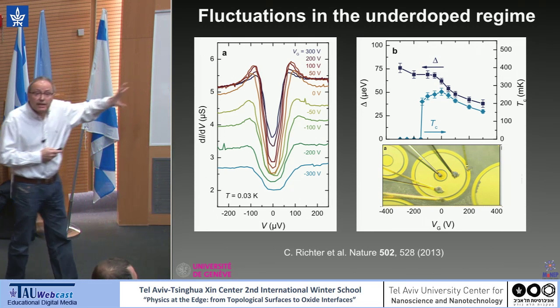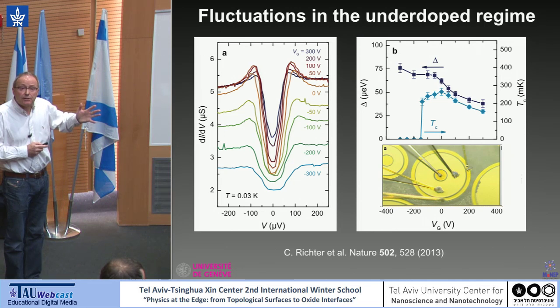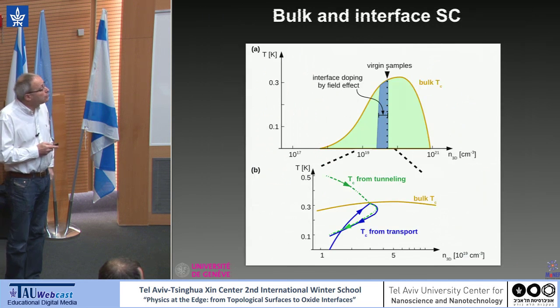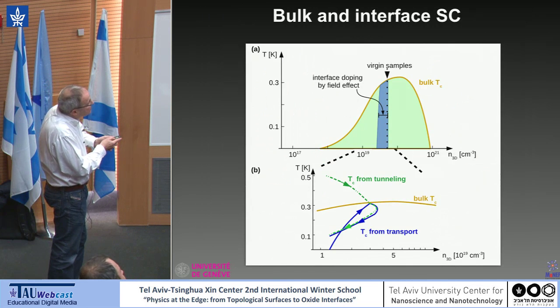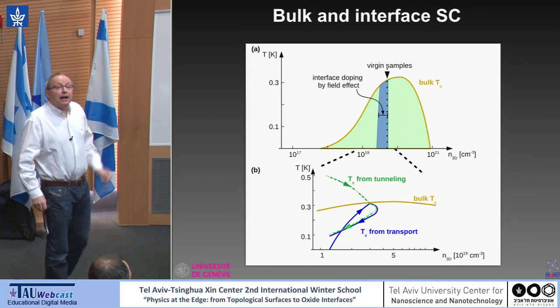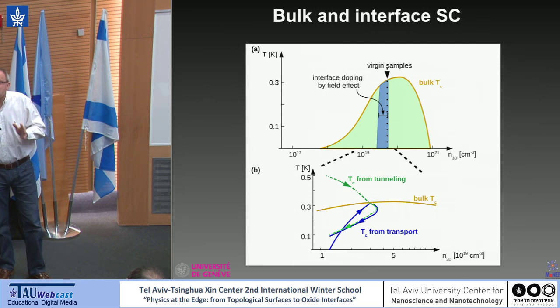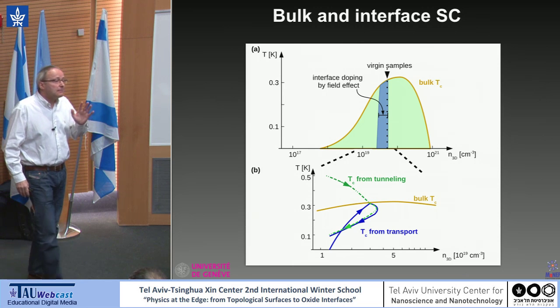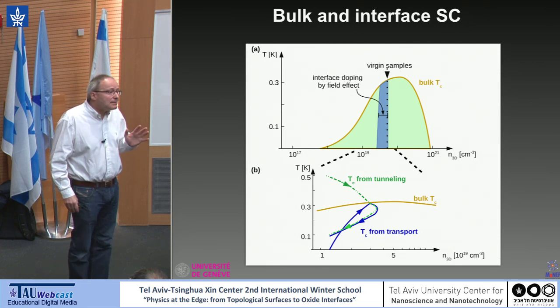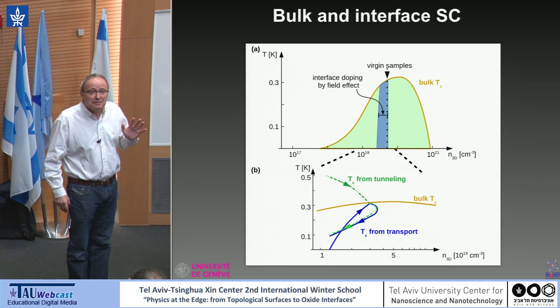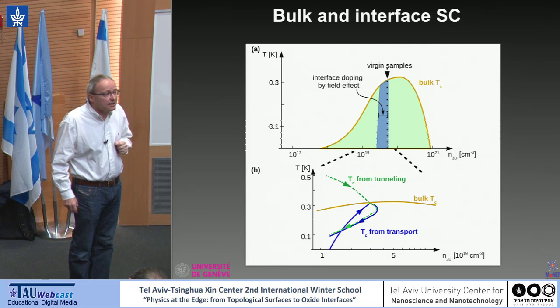But anyway, if you take this delta, you can extract the mean field TC. And if you do this, then you find that the TC from tunneling would go from the underdoped to here, and then going like this. Now, if this is the correct TC, what I was telling you about these heavy and light bands is much less compelling, because now I cannot really explain this.